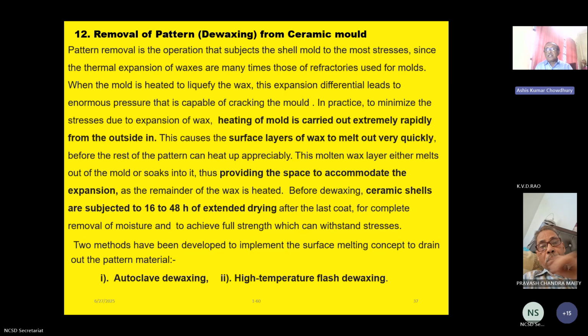The removal of pattern, dewaxing, from the ceramic mold. Pattern removal is the operation that subjects the shell mold to the most stress, since the thermal expansion of the wax is many times that of the refractory used in the mold. When the mold is heated to liquefy the wax, the expansion differential leads to enormous pressure that is capable of cracking the mold. In practice, to minimize the stress due to expansion of wax, heating of the mold is carried out extremely rapidly from the outside. This causes the surface layer of the wax to melt out very quickly before the rest of the pattern can heat up appreciably.